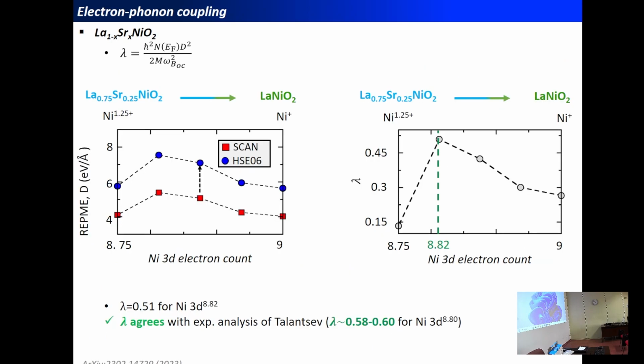And so if we do that for the different compositions within the superconducting region, we have a non-monotonous behavior for the D matrix element, which slightly increases when we add more and more electrons, and then slowly decreases. So the HSE calculation improves the value of this reduced electron-phonon coupling matrix element. And if we use that to compute lambda, the electron-phonon coupling constant, we end up with this behavior: a very low lambda at this d filling, but then it strongly increases and then slowly decreases.